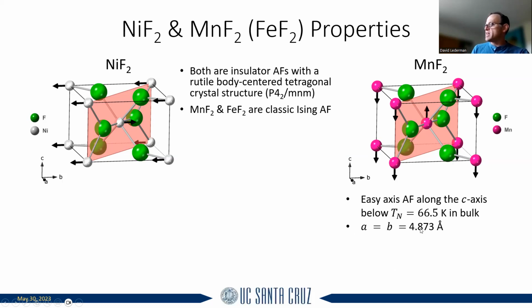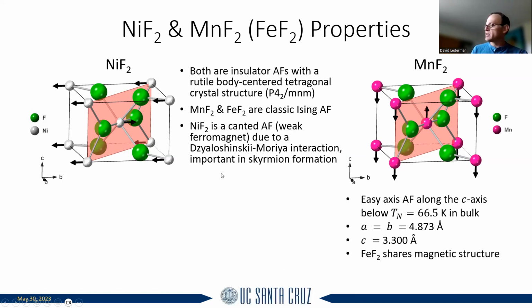It's tetragonal, so the A and the B axis have the same lattice constant. The C axis is a little bit smaller. And iron fluoride has the exact same crystal structure. The lattice constants are a little bit different, but it has exactly the same magnetic structure. Okay? Now, nickel fluoride is interesting because it's a canted antiferromagnet. That means anisotropy makes the spins want to lie in the AB plane like this, and then the antiferromagnet, instead of the two spins being like this, they actually cant a little bit spontaneously, and